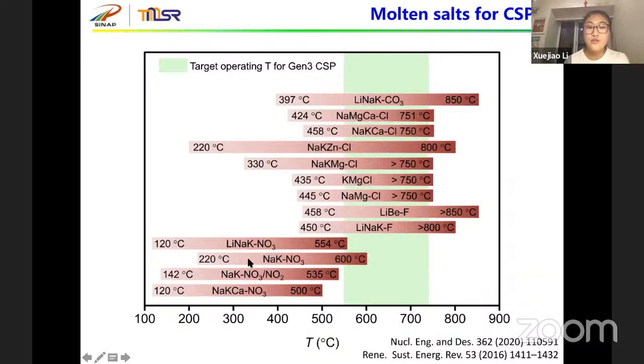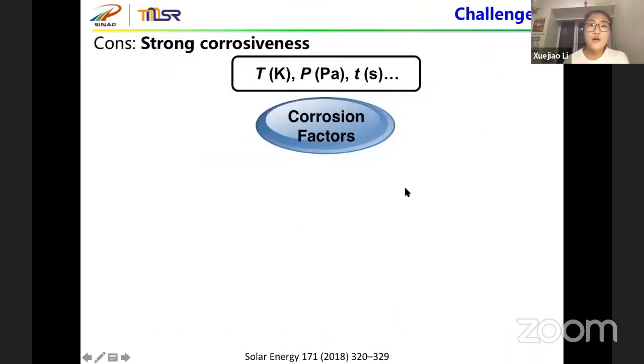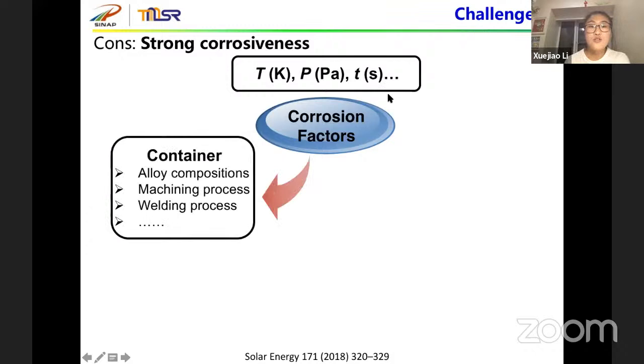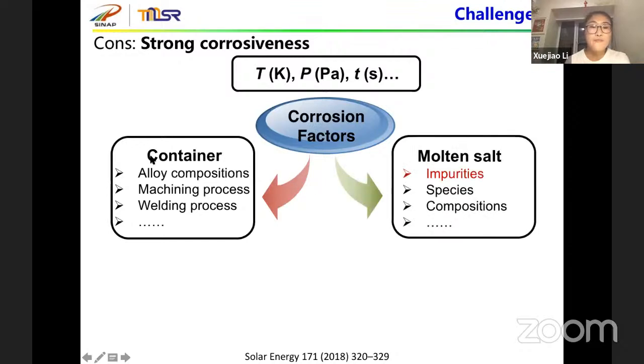The currently used nitrates, such as solar salt and Hitec salt, are not stable at high temperature. The newly proposed chlorides are suitable for Generation 3 CSP above 550 degrees. However, the biggest challenge of chlorides is the strong corrosiveness. The external corrosion factors of temperature, pressure, and corrosion time are important. Besides, the internal corrosion factors include two aspects. One is the container, the other is the molten salt. For the container, usually an alloy, the composition and the machining and welding processes are significant factors.